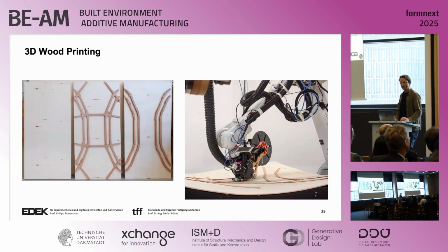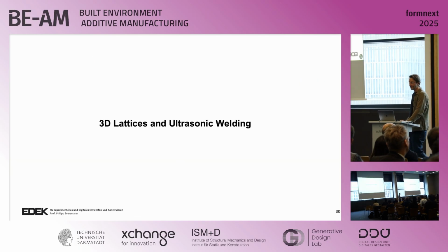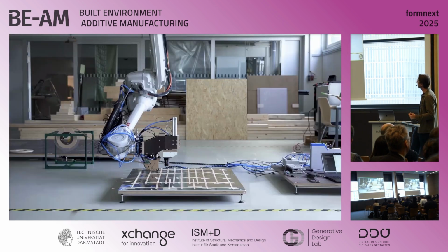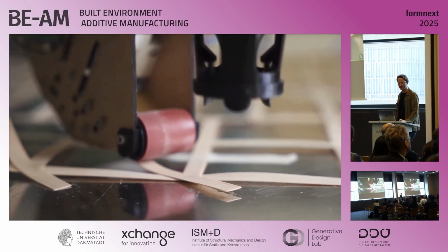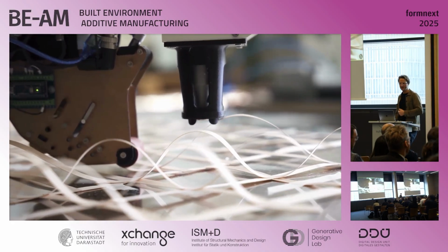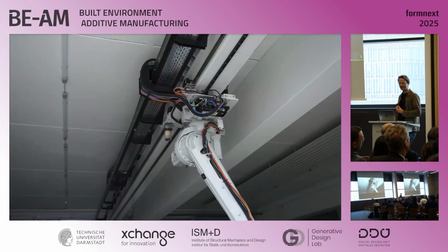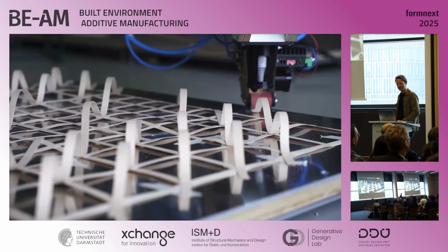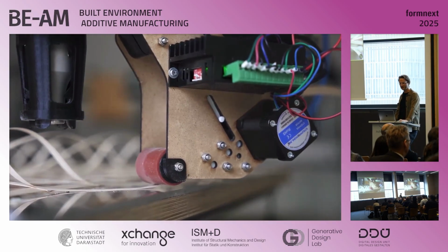Current research on that focuses on curved and also planar components, where we are also using thin wood plates as the bed for that, which stay with the component as a lost formwork. And then we apply additional layers of 3D printed timber to get more reinforcement, for slab-like systems and so on, or wall systems. We've also done more three-dimensional printing of 3D lattices, exploring also the bending potential of these. So let's say carving it through the process and getting a really high volume of components really fast. You can see this process here.